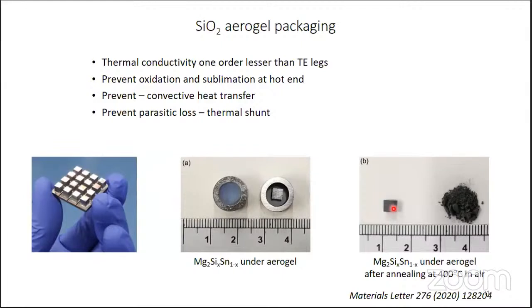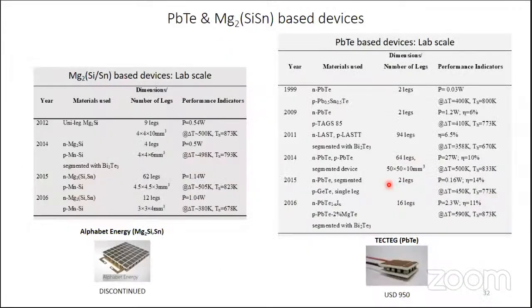So this microstructure shows the aerogel-covered Mg2SiSn. Even after 400 degree Celsius heating in open atmosphere, it shows just a few nanometer thick oxidation only. So the material is stable. But if the aerogel is not there, within a few minutes itself, all will become powder. So this is the technique we use for covering.